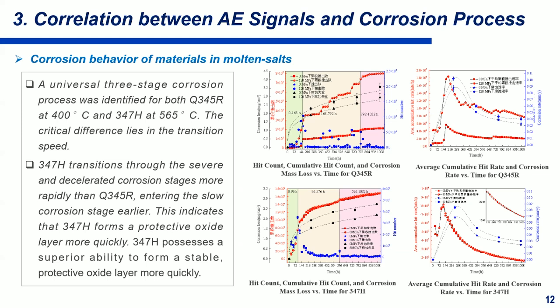A uniform three-stage corrosion process was identified for both Q345R at 400 centigrade and 347H stainless steel at 565 centigrade. The critical difference lies in the transition speed. 347H stainless steel transitions through the severe and decelerated corrosion stage more rapidly than Q345R, entering the low corrosion stage earlier. This indicates that the stainless steel forms a protective oxide layer more quickly. 347H possesses a superior ability to form a stable protective oxide layer more quickly.